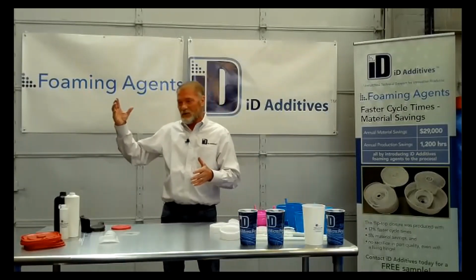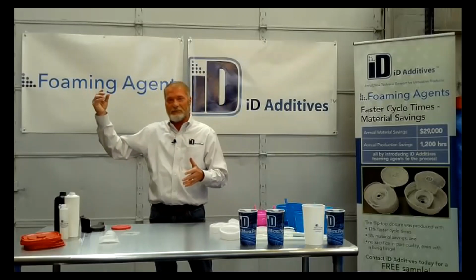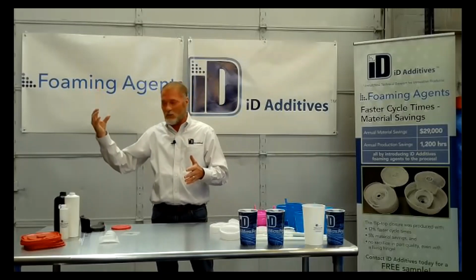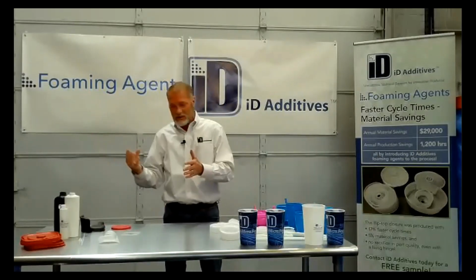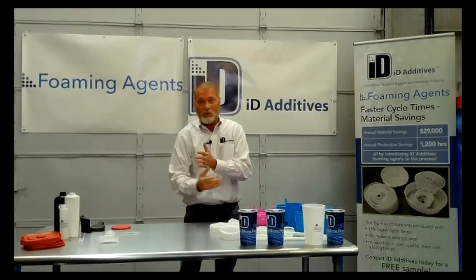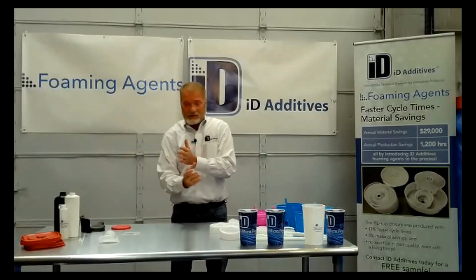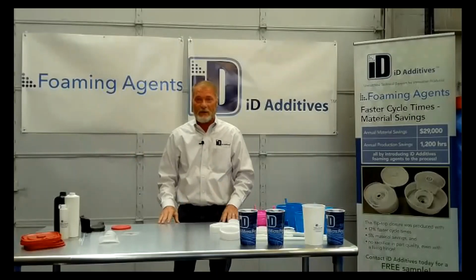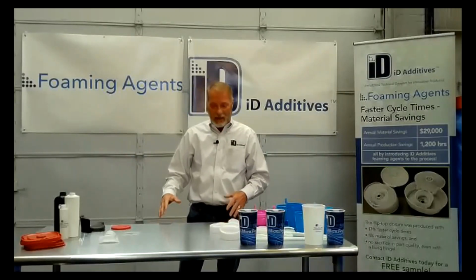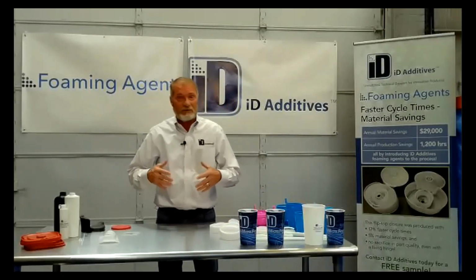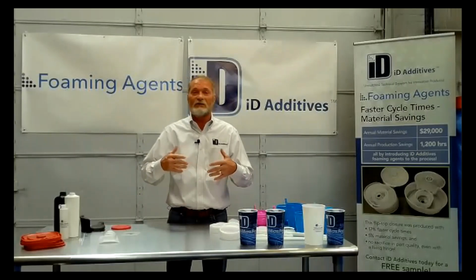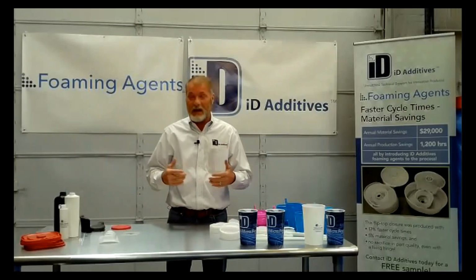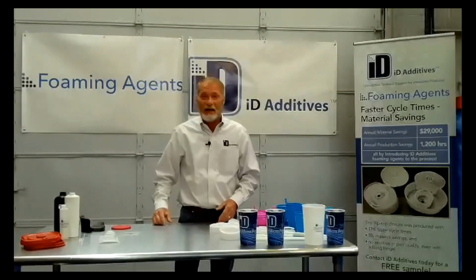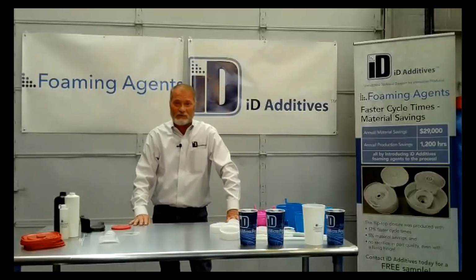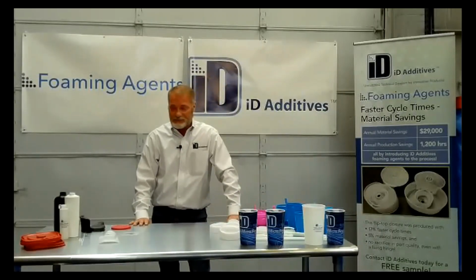What it did is it shortened the amount of time that one drop of material goes through all these cycles and hits your mold, it shortens that amount of time to where it gets in front of that screw. And then that's when you can start foaming. That way you can actually capture more gas. And they saw a whole lot of difference when they did that.